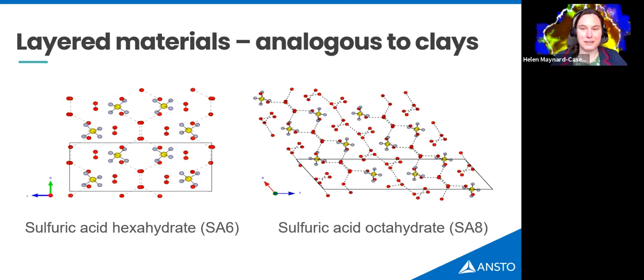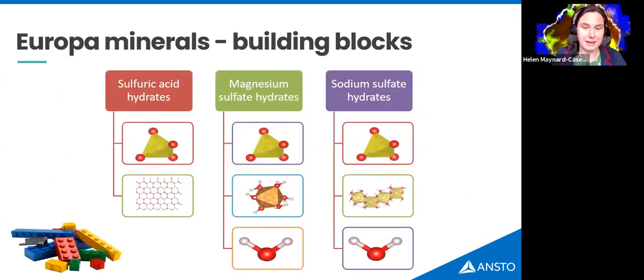And the thing is, automatically you can see that if you've got a lump of Europa, which is made out of some of its water ice, hexagonal water ice, which is actually really strongly bonded, it's quite disordered, but can be really, really strong, versus these materials, which are more layered, you've automatically got a big change in their mechanical properties. And so that can drive potential formations on the surface there.